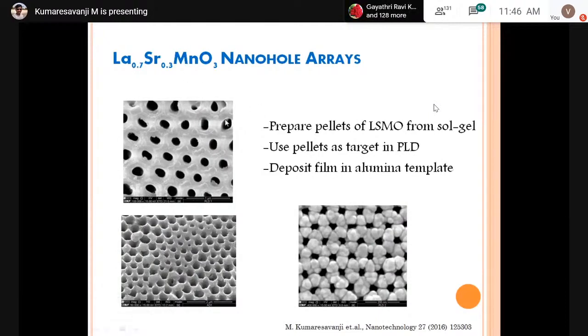For the same, I have prepared the LSMO sol-gel. Then I prepared a pellet from LSMO. Then the pellet was used as a target in the PLD, pulsed laser deposition. So just by increasing the deposition time, for example, here I deposit for 10 minutes, here I deposit for 20 minutes, and here I deposit for 30 minutes. So you can see the materials are deposited in between the holes.